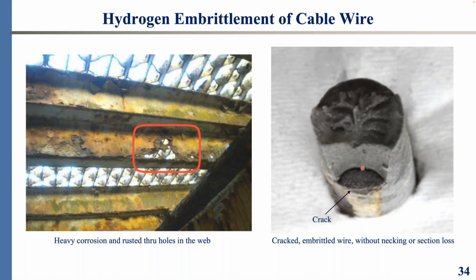You can see a big difference between this embrittled wire and the picture on the left where the laser point is hovering here, where you see heavy corrosion and rusted through holes in the web of these sleeper beams supporting a grating on the top. And this is inarguable. There's a big difference between this mild low carbon steel and the very high carbon steel that exists in the bridge wire. It's a different phenomenon. In fact, case in point, when was the last time we had to replace cable bands on a suspension cable because the cable lost mass or lost weight, for that matter, because of the loss of material? The answer is never.